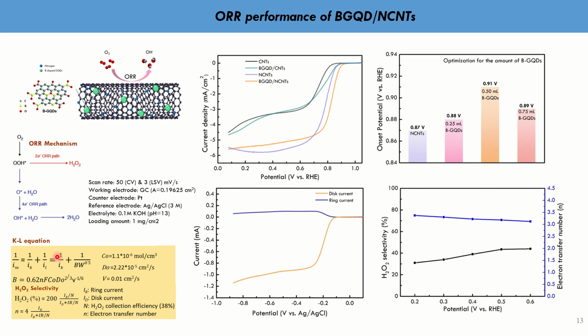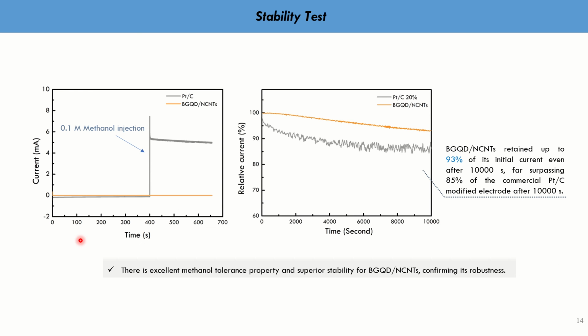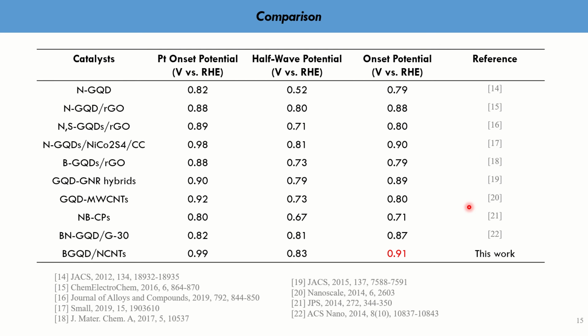Methanol tolerance is a crucial issue for the development of platinum-based ORR electrocatalysts. After adding methanol, there is no current difference for the BGQD/NCNT electrocatalyst. The current retention of BGQD/NCNT is 93%, superior to platinum in the long-term stability test. Compared to other graphene quantum dot or carbon nanotube-based ORR electrocatalysts, BGQD/NCNT possesses the highest onset potential.